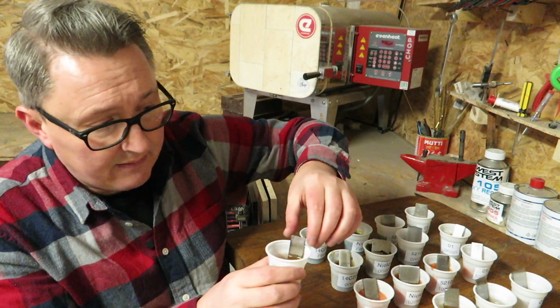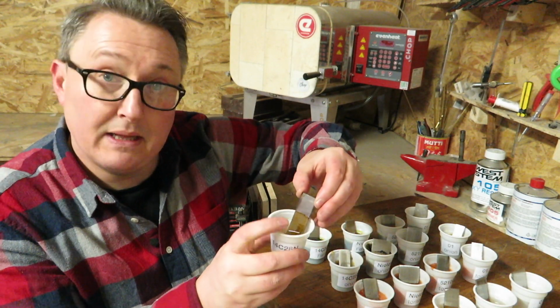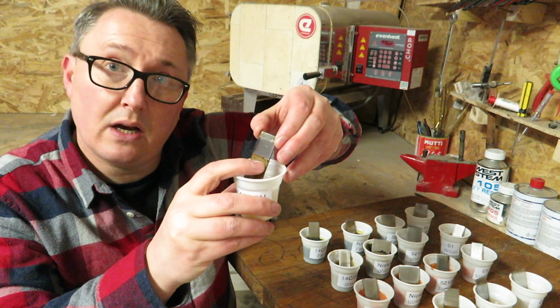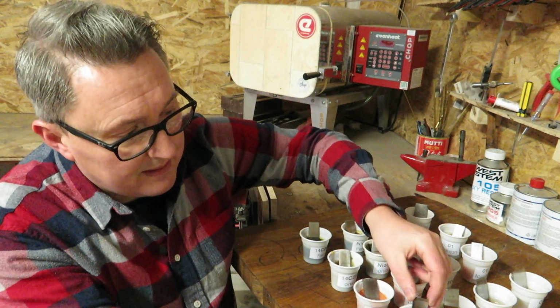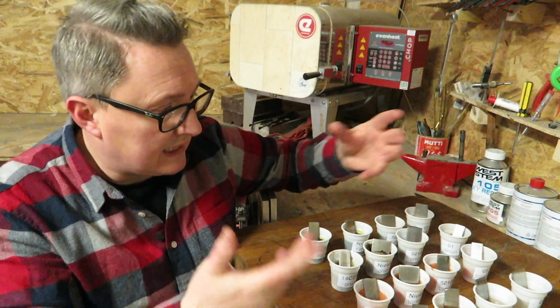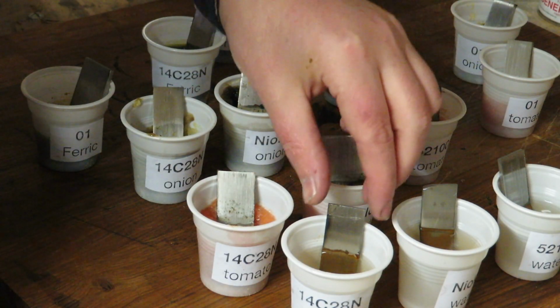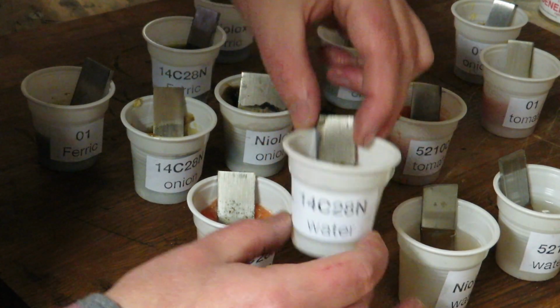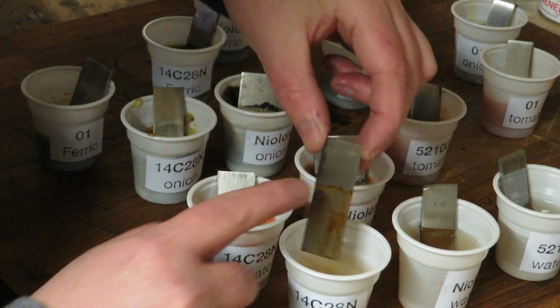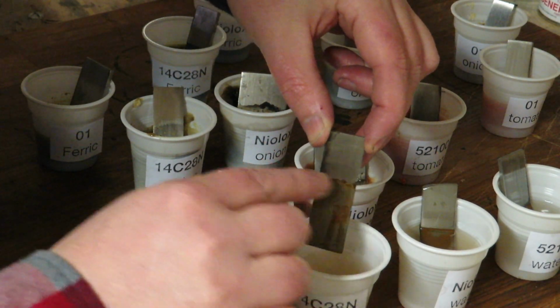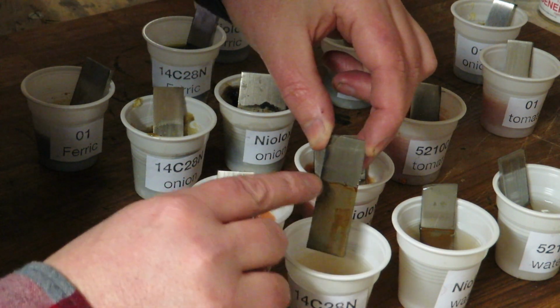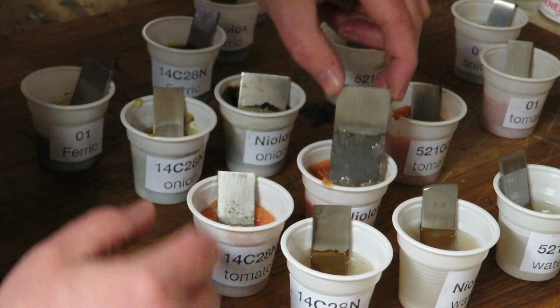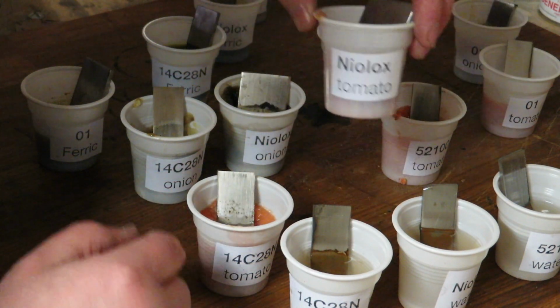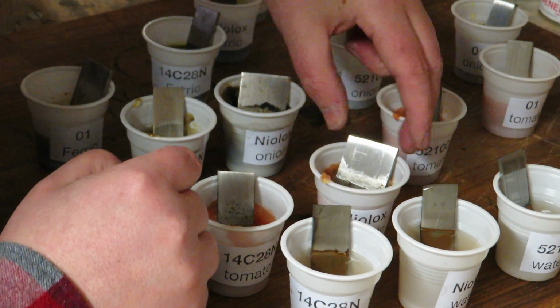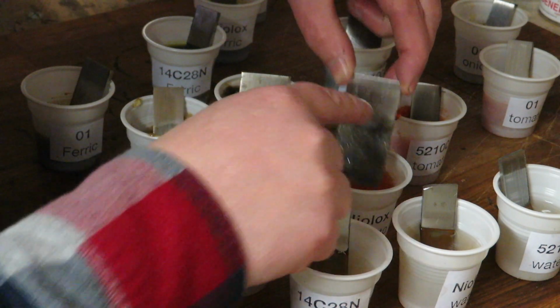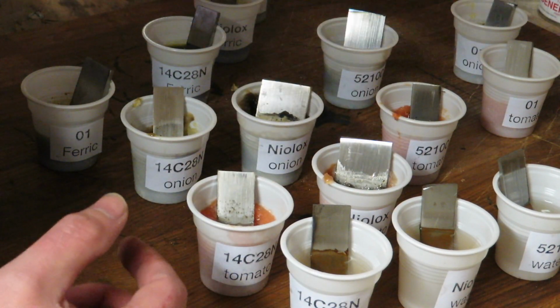And you can see it here, even with the stainless in the water. You can see there that line, and I think that means that is where it's hit the oxygen. So if we have a look here, even with the stainless, the 14C28N, just where the steel hits the surface of the water, we're seeing a lot more corrosion. And that seems to be right across the board here. So we've got the Niolox in the tomato, and that's happened the same here. So right where the surface line is, we're seeing more corrosion.